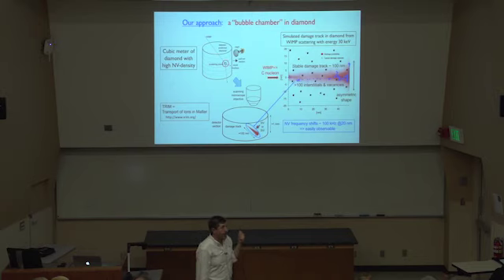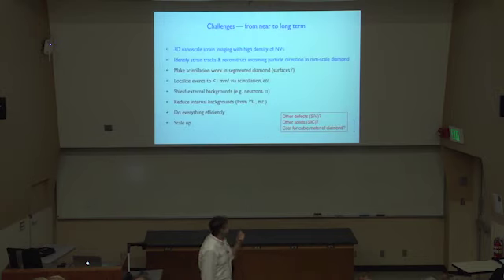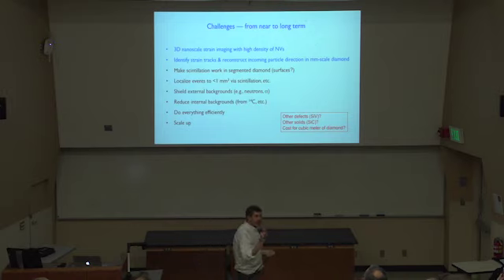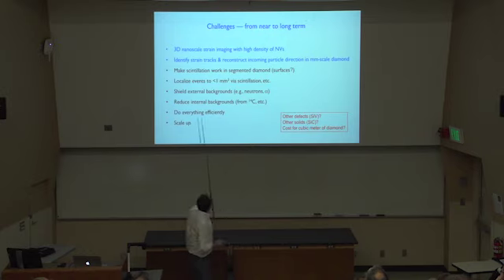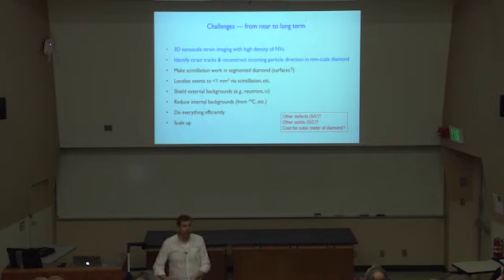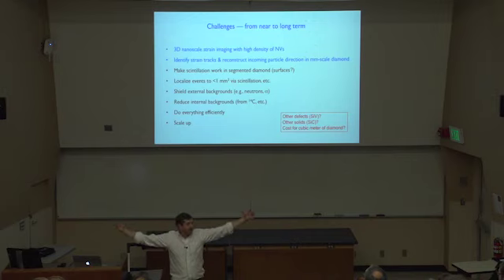The challenges are many. We've done strain imaging with that sensitivity. We've done nanoscale magnetic sensing with that sensitivity, at that spatial resolution. We haven't yet done 3D strain mapping on the length scales and with the sensitivity we need, but I don't think that's going to be the problem. I think identifying and reconstructing the particle direction, if you had enough information, would be fine. I think you're going to have a series of problems like, one, finding the little small region, 100 nanometer region, that potentially has strain in it inside a millimeter region is going to be a problem. So we're thinking about ways to scale that problem and make that easier.